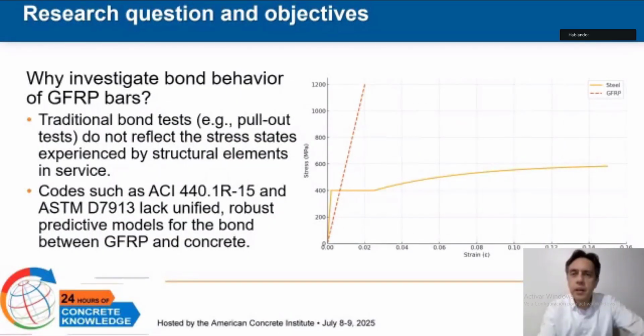This figure compares the typical stress-strain behavior of steel and GFRP reinforcements. The GFRP curve on the right exhibits a linear elastic response up to failure with no yielding, resulting in a brittle rupture around 1200 megapascals. This behavior is governed by its lower modulus of elasticity of about 60 gigapascals and the absence of plastic deformation. In contrast, the steel curve shows a well-defined yield plateau beginning at a strain of 0.002, followed by strain hardening beyond 0.025. This ductile behavior allows for energy dissipation and is central to traditional design approaches.